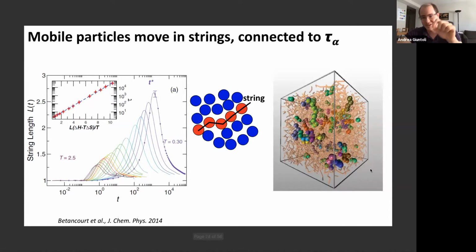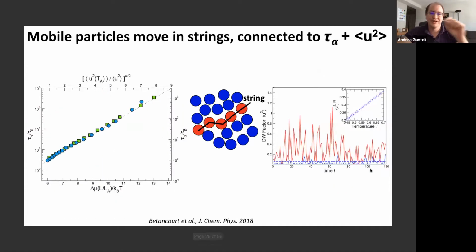You can see these strings moving around in the simulation. And you can show here on the left that the length of the strings is related to the alpha relaxation time and also to the Debye-Waller factor, of course. It's all linked. That's not surprising because if you look to the right, you'll see that the contribution of the mobile particles to the Debye-Waller factor is actually much larger than the contribution of the immobile particles, the blue line.